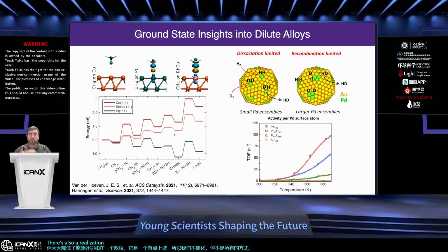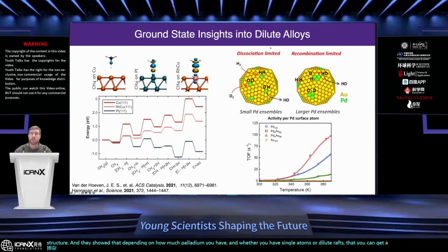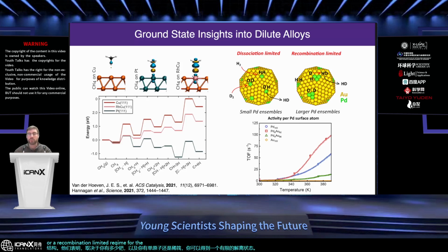There's also a realization by others in the community, this work comes out of the lab of Cynthia Friend at Harvard, that we don't necessarily need individual atoms to make this chemistry take place. We could actually have a small amount of dopant. In this case, they synthesized gold palladium nanoparticles, and they looked at the regime where you have individual single palladium atom dopants, but then also small clusters or rafts of palladium inside the structure. And they showed that depending on how much palladium you have, and whether you have single atoms or dilute rafts, that you can get a dissociation limited regime or a recombination limited regime for the hydrogen dissociation reaction. So again, it's a model system, but it shows and demonstrates, and I think there's been some other work as well recently that shows that you don't necessarily have single atoms to really push this forward.